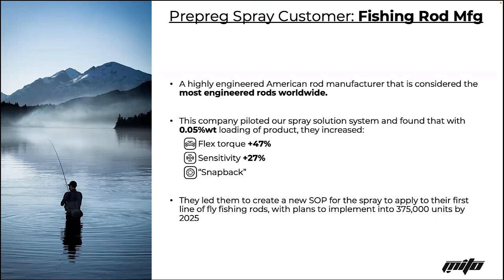So with 0.05% by weight, they were able to increase flex torque by 47%, the sensitivity by 27%, and snapback, essentially how quickly it settles back to shape. And that was just with a spray solution onto their prepreg, so they didn't have to go through the compounding process. This product can be made into a prepreg, but going back through that supply chain can be very long and tumultuous and take years and years to enable that material adoption.